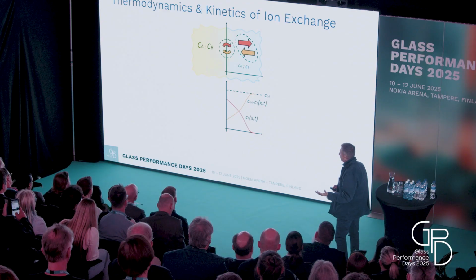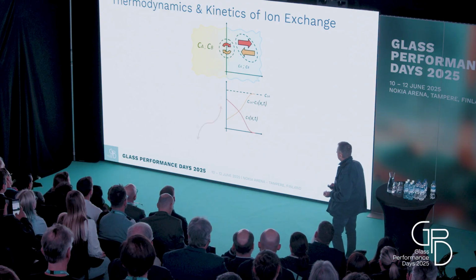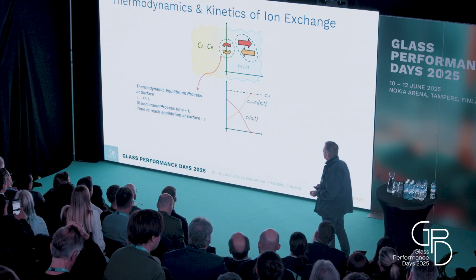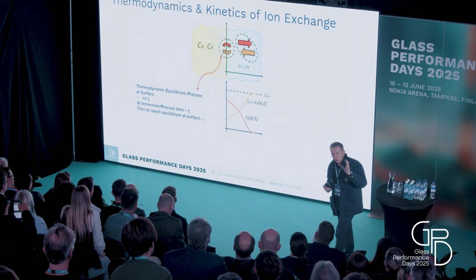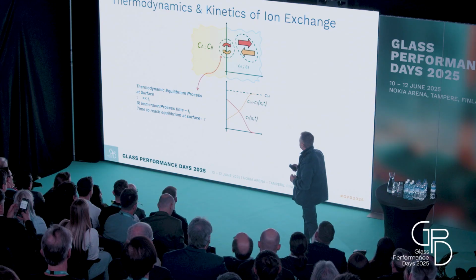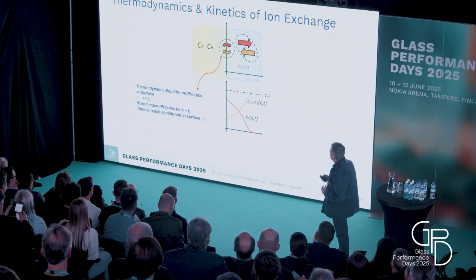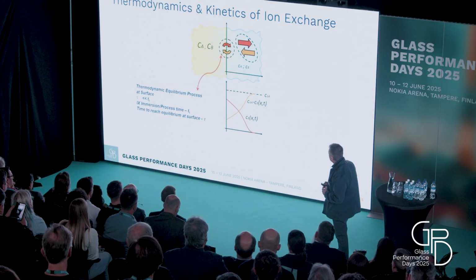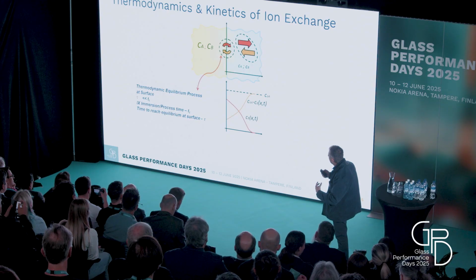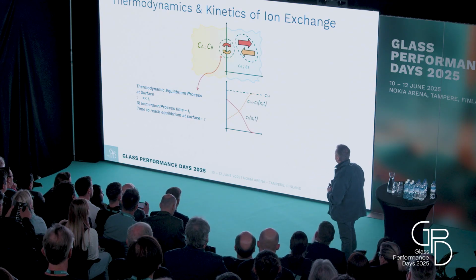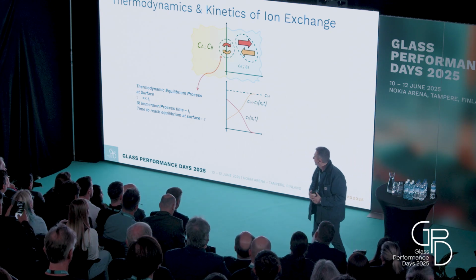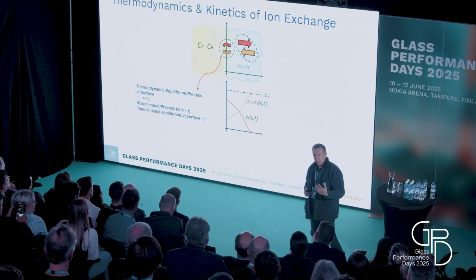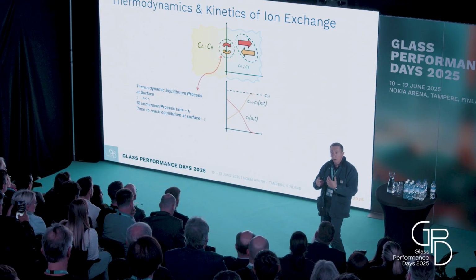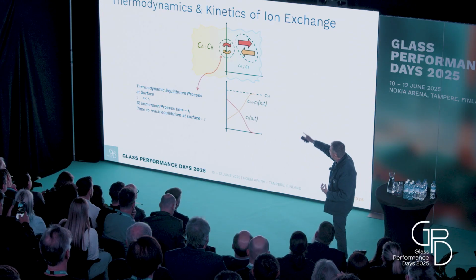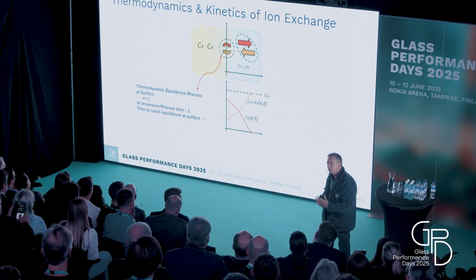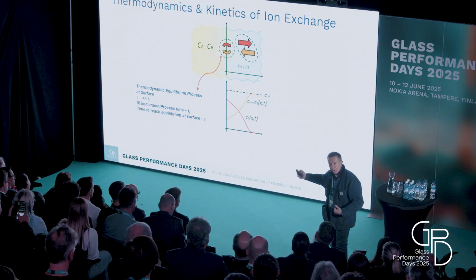So we have to discuss two elements, the thermodynamics and the kinetics of ion exchange. The first assumption that we will make is that this process can be divided in two parts. One is a surface process, which is in some way dominated by thermodynamics, and a bulk process, which is a kinetic process. And the surface is very important because if the time to reach the equilibrium at the surface is much lower than the total contact time of the glass with the salt, then you can treat that in terms of thermodynamics. Thermodynamics is a science of equilibrium, but this process is a non-equilibrium process by definition. So you have to assume that the time to reach equilibrium is much lower than the contact time, otherwise you cannot use thermodynamics.